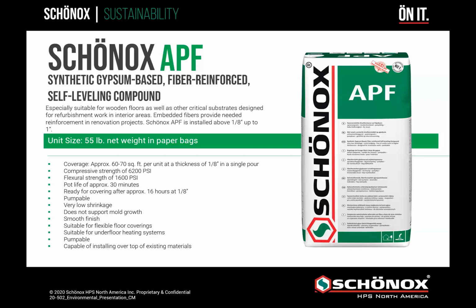It's especially suitable for those wooden substrates and other critical substrates, especially in our multifamily applications, in our high-rise and our mid-rise. These embedded fibers give the rigidity and the reinforcement that we need in these renovation products. Schönox APF is installed between 1/8 of an inch and 1 inch. Now we have a compressive strength of 6,200 with a flexural strength of 1,600. Ready for floor covering after about 16 hours.